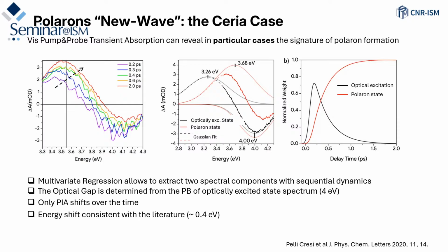And if you just consider that the bleaching of the valence band should mainly stay at this energy, so 4 eV, which allows us also to report a proper way to define the optical gap of the material, we can only imagine that we have this shift induced by the photoinduced absorption. We, of course, try to fit those spectra. We observe that the shifting of the photoinduced absorption, so the localization of the deformation of the polaron, induced this blue shift, which is compatible with the polaron formation energy for the cerium oxide from calculation.